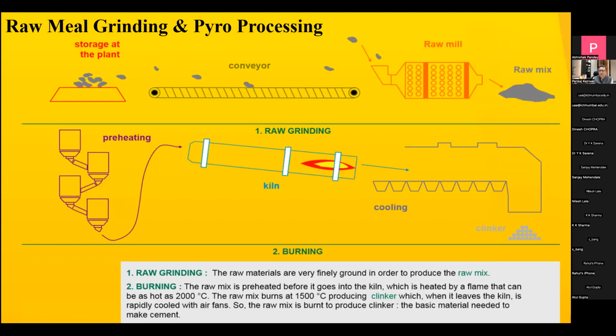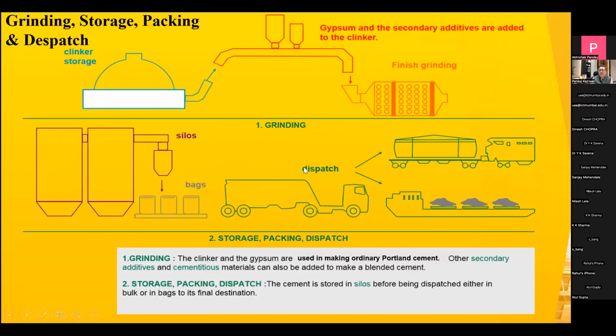This clinker, we then put to the cooler, where it has to be cooled very fast so that it forms the proper crystals. The product coming out of the cooler is called clinker. This is basically where about 60 to 70% of the entire process is completed. In the next stage, once the clinker is made, we take it to another grinding mill, where we earlier used to add only clinker and make OPC cement, whereas now we add the fly ash or the slag and make the other kind of blended cement. The cement coming out of the grinding mill is then stored in silos. After the silos, we pack it through automatic packers into bags and then dispatch it to the market.